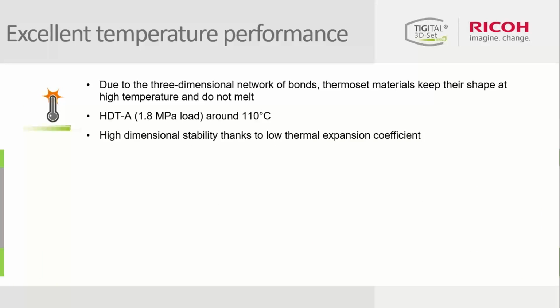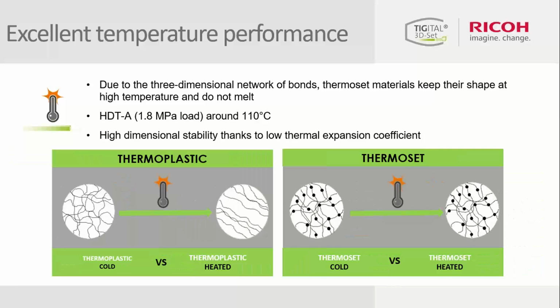And also the fact that the material, when exposed to a source of heat, can keep its shape at this high temperature is due to the fact, as I mentioned before, that during the printing process we really create a three-dimensional network of chemical bonds between the polymer chains of the material. And basically what we are doing here during the printing process with this type of material is using the laser in the printer to create a chemical reaction between the polymer chains rather than melting the material as it happens with thermoplastic material.